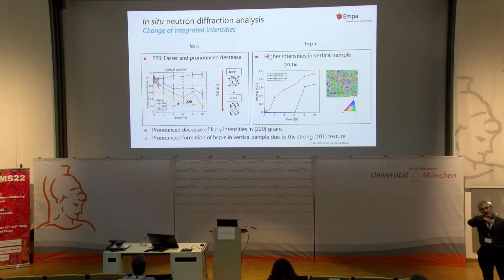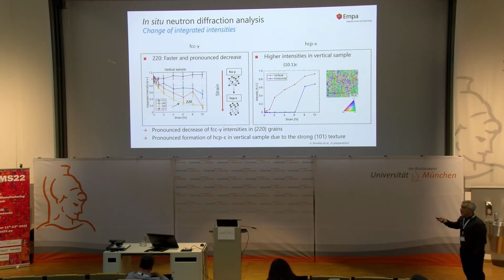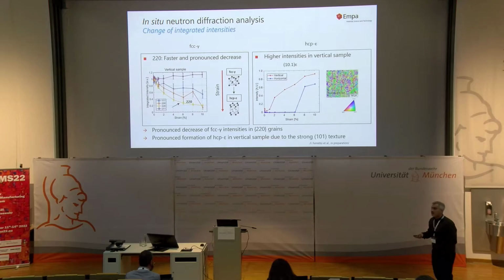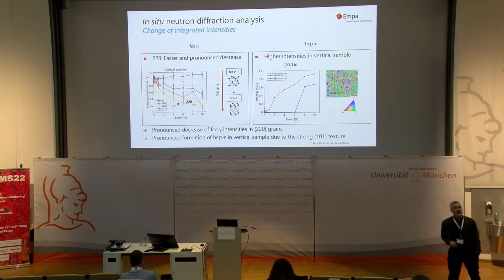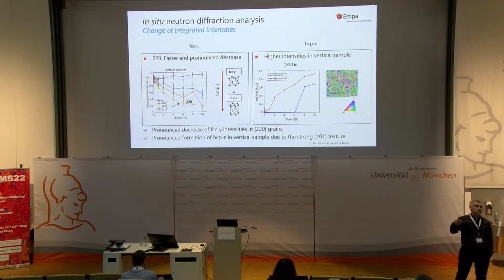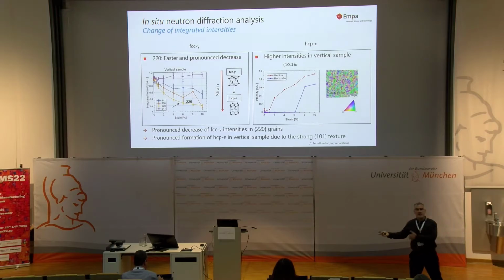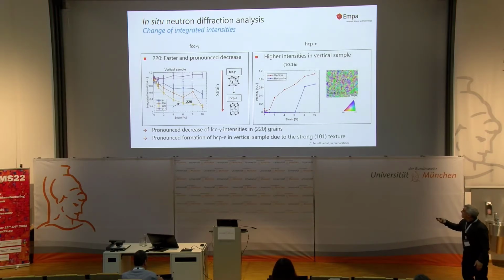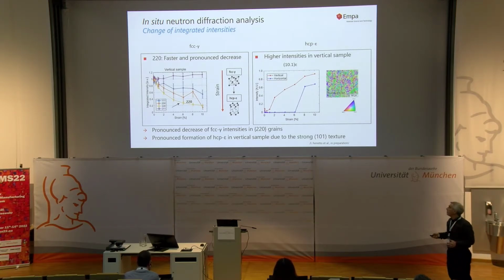So first, what we looked into are the integrated intensities, first for the two phases, but as a function of the grain families. So we looked into, for example, 111, 200, 220, 311. And you can see that as a function of the applied strain, first of all, the intensity of the gamma peak decreases. So not surprising. This means it has to transform into something. It's no more gamma afterwards. And what you can also see, there is a very pronounced difference between the grain families. So we have here this 220, which shows apparently a very pronounced transformation, and we have other grain families which show no transformation at all, and start to rotate and do some other things.